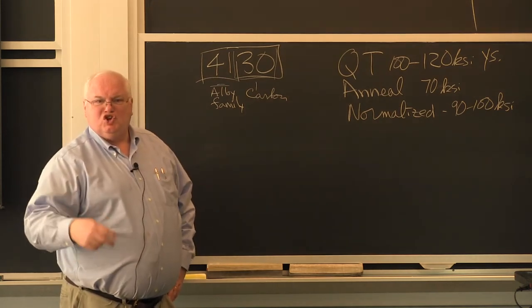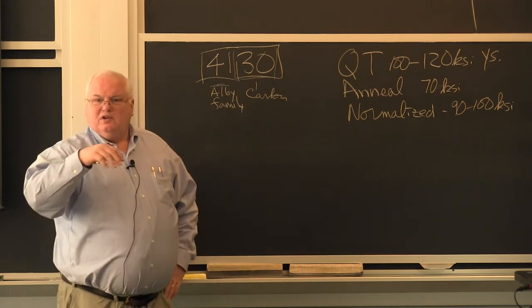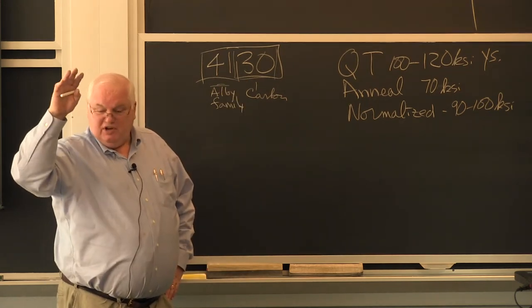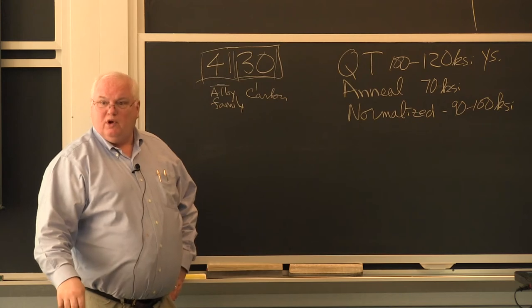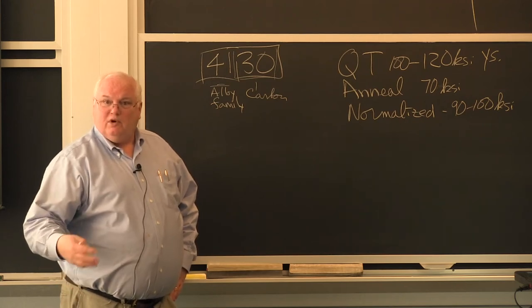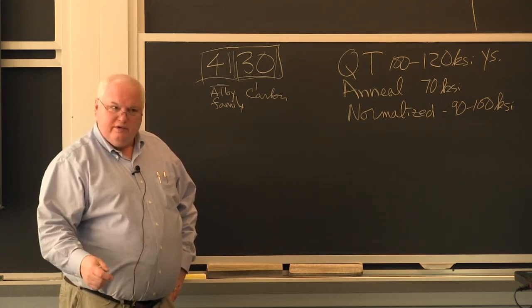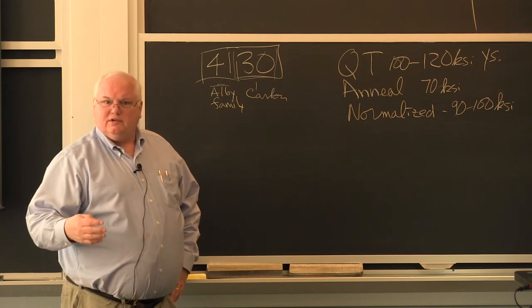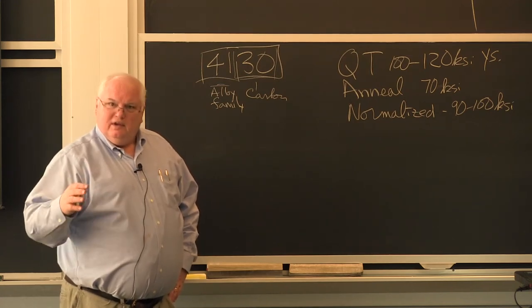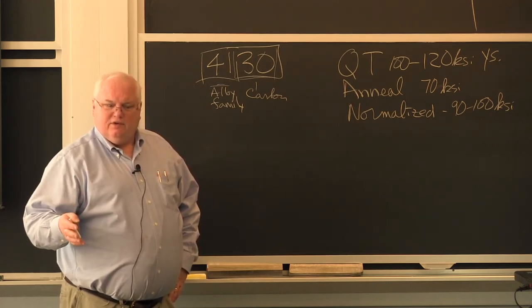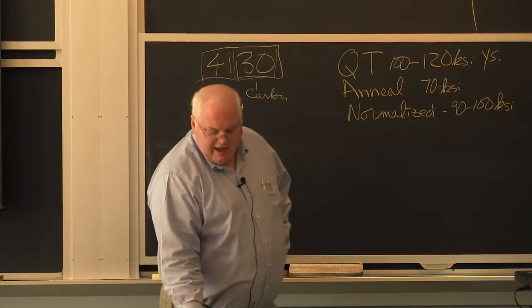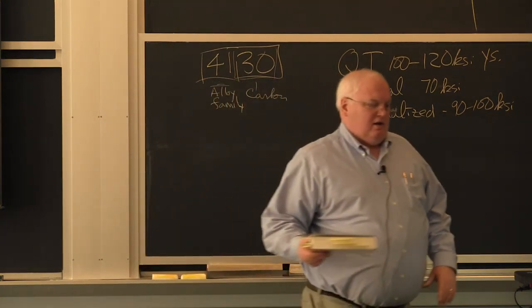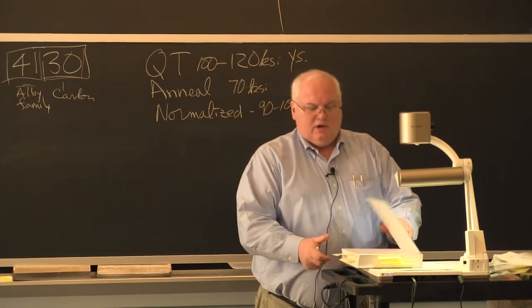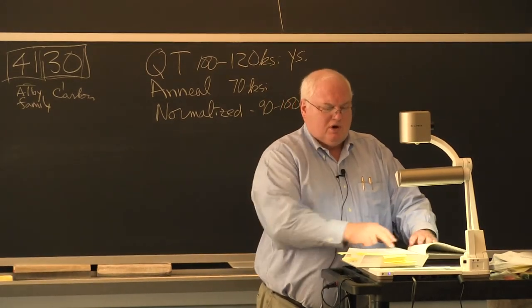You need something to slow down the transformation, because the thing doesn't cool immediately when you put it in water. It takes a little time for the water to, you know, when you first put it in the water, you get boiling heat transfer on the surface, and that's not very effective. It takes a little time. It takes seconds for this to occur. And I don't always have seconds, okay? If I start looking at a steel transformation book, and this, I'm sure you all have these.